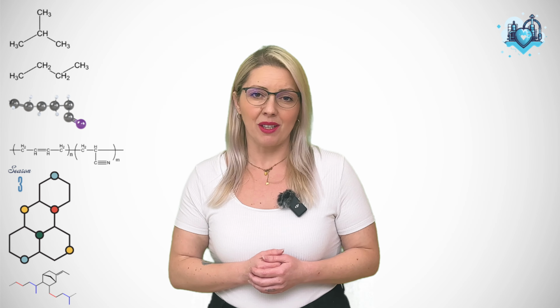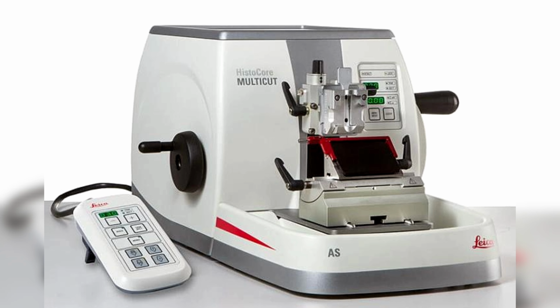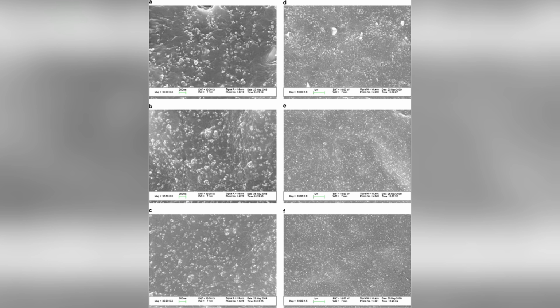And dispersion isn't something you guess at. You can evaluate it directly. In development labs, we often use microtome slices and look at them under the microscope. You can see the filler clusters clearly. Dark spots for carbon black, bright particles for silica. Smooth, even fields mean success. Big clusters mean the mixer struggled. Some labs use dispersion rating scales, level 1 through 5, or percent undispersed area, to make it numerical. And factory lines often use quick cut and peel tests or dispergrader images to check batch-to-batch consistency.